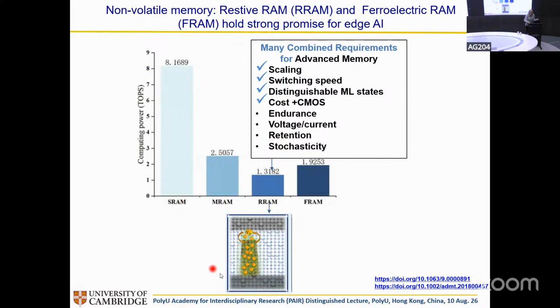And if you look here, this is the resistive technology, showing how it works in oxide resistive materials, which is the most common type and the most cost-effective, let's say. You have the formation of a filament based on oxygen vacancies. And the top of this filament can be switched on and off with a field. So you move the vacancies, either forming a complete filament, or you move them away and then you form a cut-off filament. And that gives you high and low resistance states.